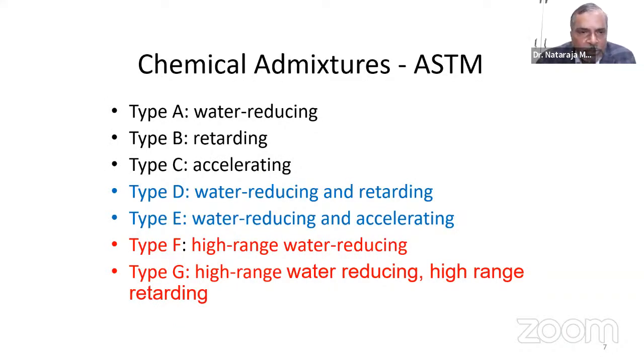The next important thing I was mentioning is the use of chemical admixtures. If you see the American Society for Testing of Materials code of practice, different types of chemical admixtures are permitted: type A being water reducing admixture, type B retarding admixture, type C accelerating admixture, type D water reducing and retarding admixture, type E water reducing and accelerating admixture. And in the current work we have done, in one way or the other, we are using type F and type G, where type F is high range water reducing admixture. These are referred to as superplasticizers or hyperplasticizers in our country. We also have high range water reducing and retarding admixtures, very close to hyperplasticizers, with an accelerating or retarding effect depending on the situation.